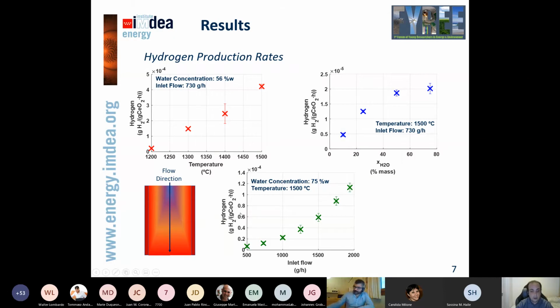And we think that this may explain the big gap, where production increases more or less 6 times in the data we used. This may be because we are not really doing an isothermal test, but with the liquid water injection, we're creating 2 areas in the reactor. One of them at low temperature and another one at high temperature, in which the reduction takes place, and then somehow it promotes the vacancies to the, let's say, hydrolysis part in which we produce the hydrogen.